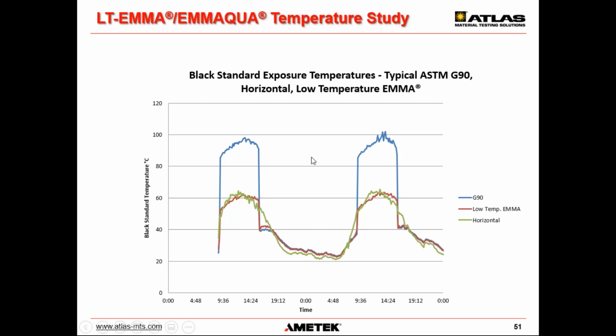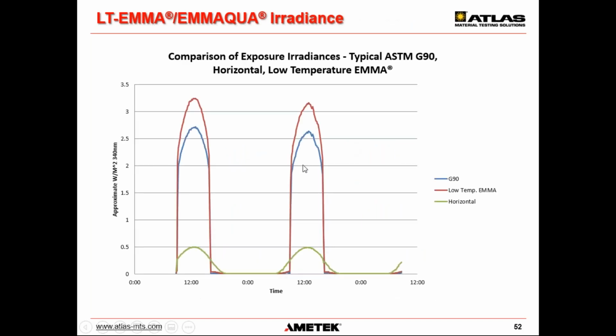We did not hold the temperatures very well with the traditional EMMAQUA exposures, but we do get that higher amount of radiant energy. Here you see with the low temp EMMAQUA, the radiant energy during the course of 2 days versus traditional EMMAQUA, where the reflectance in the UV is actually higher with our cool mirrors, as compared to the radiant energy that we get on a traditional static horizontal exposure rack.